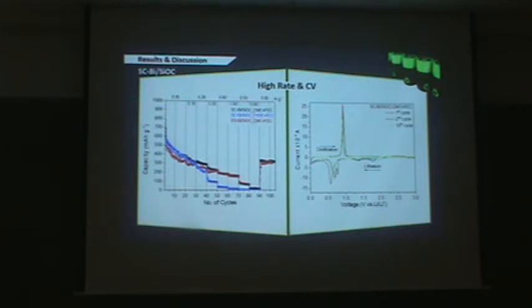And then lastly, from the CV, we can interpret that the sample undergoes a two-phase transition from bismuth to lithium bismuth, followed by lithium 3 bismuth during discharging, and then a single phase transition during charging.